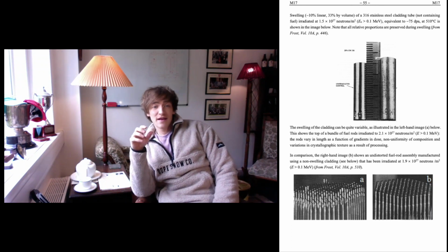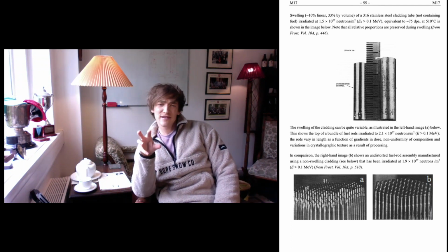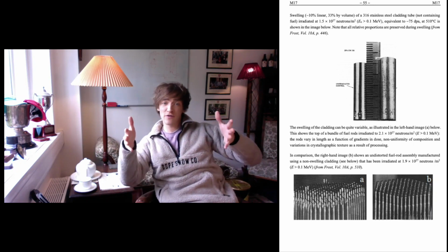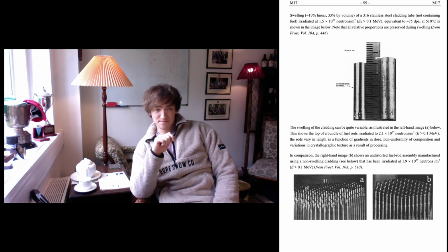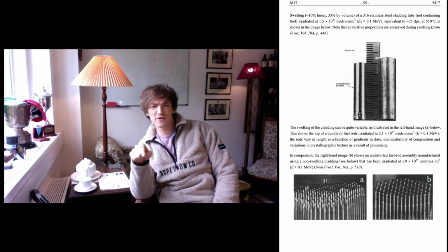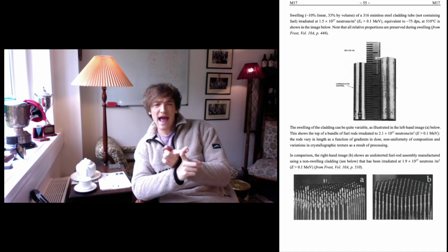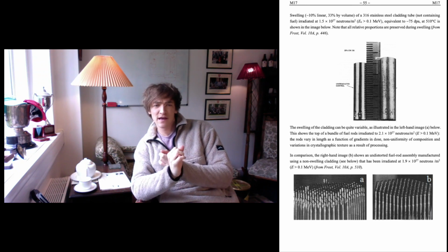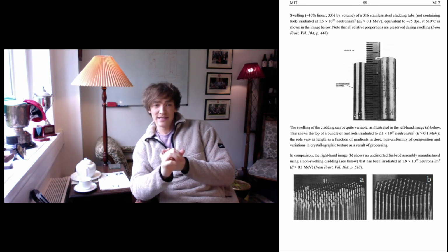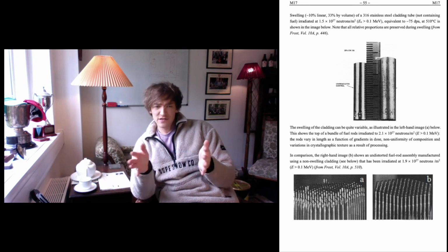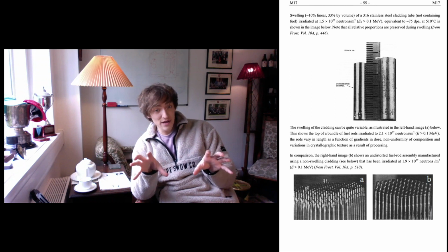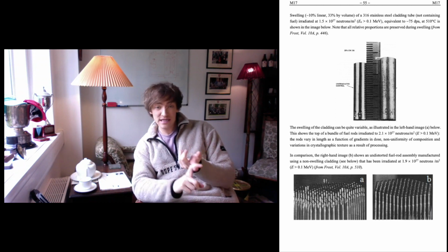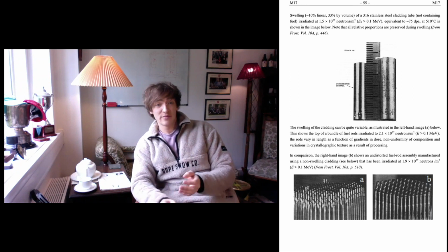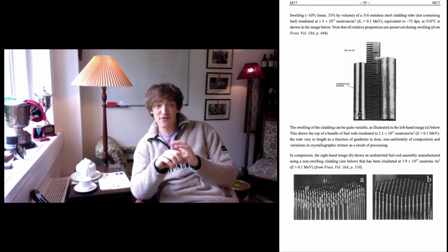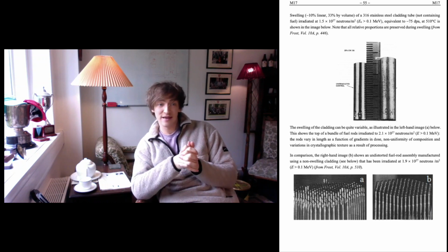Now, although that is the case, if you were to look across a whole fuel assembly, you might see something like the image below. What you're seeing there is the top of two different fuel assemblies after irradiation. Figure A shows an irradiated bundle of fuel rods with various heights due to the variation in dose that you're getting across those fuel pins. And, most importantly, non-uniformity in composition and texture of the rods. So because the composition and the texture were different, the rods are going to react differently to the swelling.